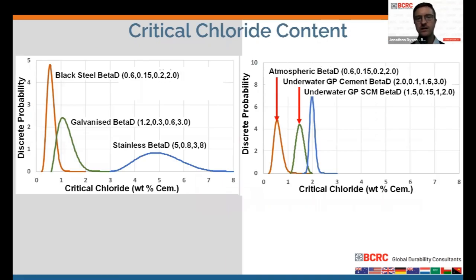So this is just another slide, just an example of one of the parameters that goes into probabilistic modeling and how it's a variable. It's not a single value. Chloride content, the critical chloride content that initiates reinforcement corrosion in concrete. Now, that's different whether you're talking about mild black steel, or if the steel is galvanized reinforcement, or if it's stainless steel reinforcement. Those variables are different. And that's different in terms of the mean value that initiates the corrosion. Obviously, galvanized and stainless have higher mean values of chloride content before corrosion will initiate.